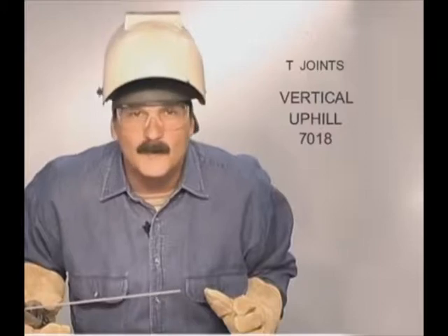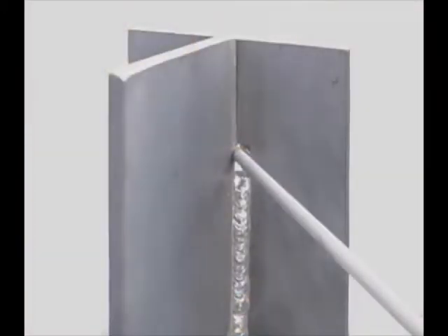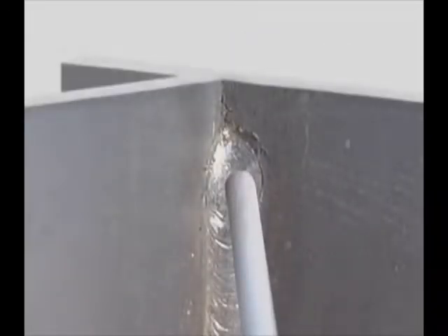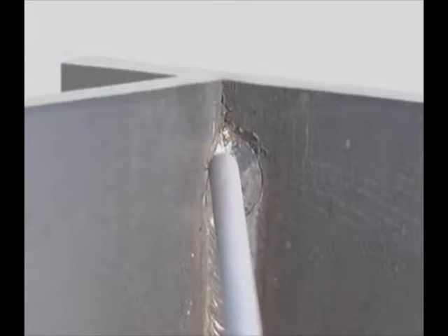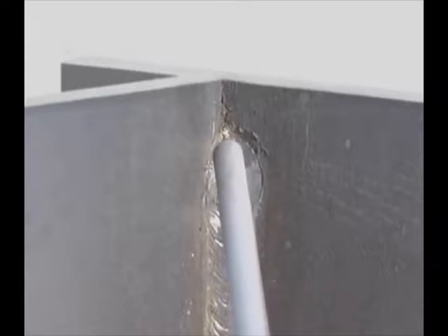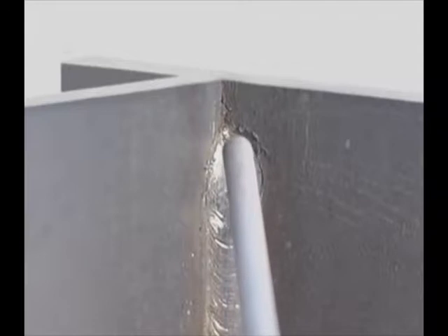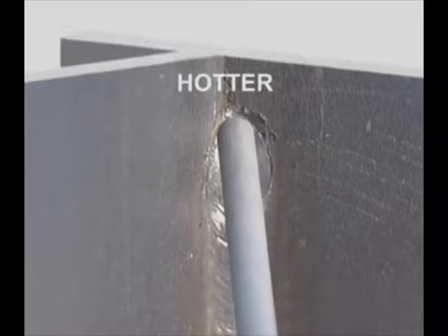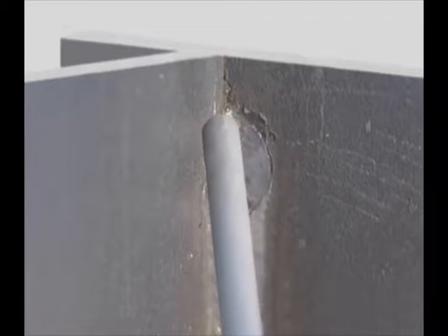70-18 uphill will build weld faster. For the first pass deep in the corner, angle the rod up slightly. Pay attention to the arc gap, following the base metals into the corner and along the sides. This is very subtle. It's just a little movement into the corner as you're coming across, but jamming the rod into the sides cools the weld down, and long arcing across the center creates more heat.